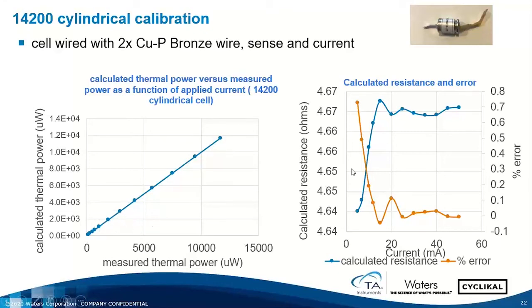On the right here is a plot of the calculated resistance. And on the right-hand axis here is the percent error. Typically, for a lot of our experiments lately, we're working in the 20 milliamp range. And that's the area that we tend to calibrate in. And you can see we get pretty decent accuracy of the thermal power going through that calibration.